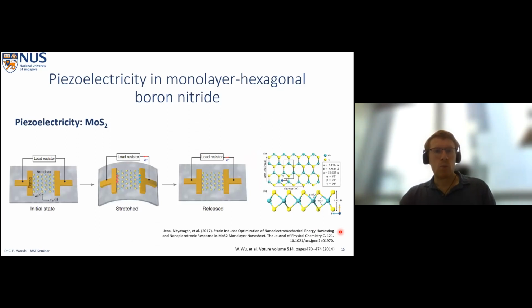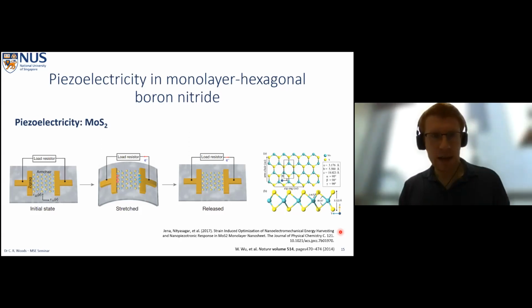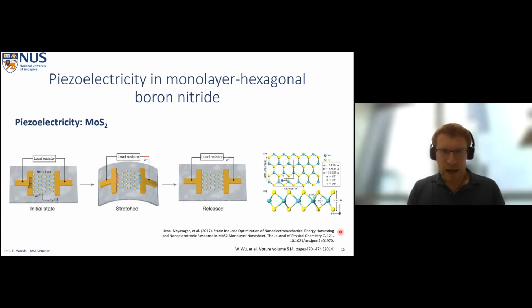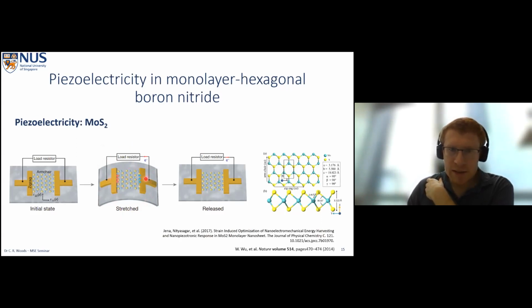Okay, so where does piezoelectricity fit into two-dimensional materials? Well, it's already been demonstrated for molybdenum disulfide, the transition metal dichalcogenide. And what these guys did in 2017 was they put their MoS2 on a polymer and they flexed their polymer, you can see here. And by flexing it, they introduce uniaxial strain from one end to the other. And they can use this by flexing it backwards and forwards to drive current through a series circuit. And this is quite a cool result, and it's quite a nice paper they produced.